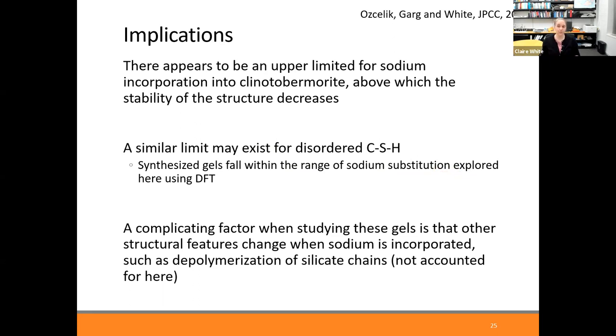And this is still to be proven the case, because what we're doing here is we're using a model crystalline structure to infer what is likely occurring in the disordered gel. But without looking at the disordered gel directly, we can only infer. We can't prove that it's the case. And so, for example, there could be ways of using, say, force field molecular dynamics simulations to explore the same question, but you're looking at also the impact of disorder on the system, so that you're more representative of what we know these gels to be like in real life.